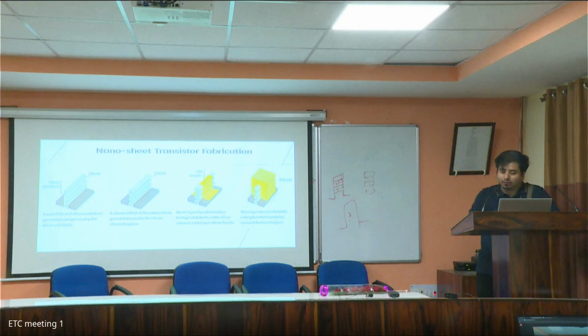Correct. So for DIBL, I think since FinFET, we don't use any doping in the channel. In planar, we used to have doping because, as you mentioned, those are the counter dopings, like halo dopings, to control the short channel effects. From FinFET onwards, we completely rely on the gate control, and that's why we eliminate any halo doping in the channel. It's mostly undoped channels, and that helps us because now it can enhance the mobility of the channel by itself.